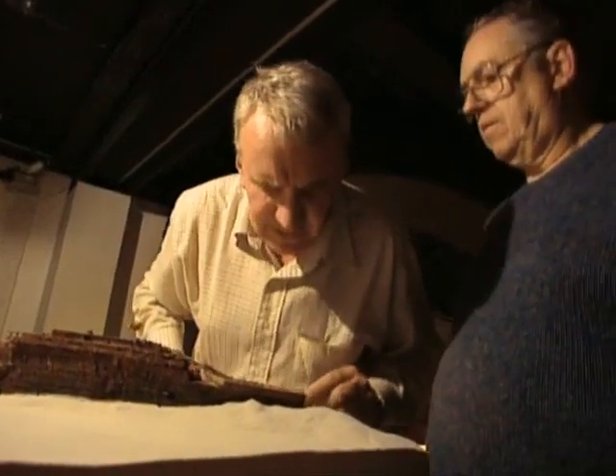They believe that as the bow dropped, it was already filled with water, so it was not crushed by the increasing water pressure. The bow actually is in good condition compared to the stern because of the equalization of pressure during the sinking process to the surface. The model is not strictly correct.